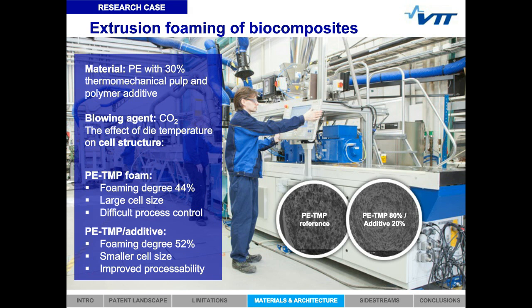Here is one example showing how we have been able to improve the processability of biocomposite materials in the extrusion foaming process. In this example, we had PE material filled with 30% thermomechanical pulp. The foaming agent we had here was CO2 and we used an extrusion foaming process. With the reference material, TMP reinforced PE, we had difficulties maintaining the process stability. The process was very unstable. We ended up having very large cell size, and the distribution of cells was inhomogeneous in the material. However, when we used a certain polymeric additive in the process, the foaming process became stable, the cell size was significantly reduced, and the foaming degree was also improved.